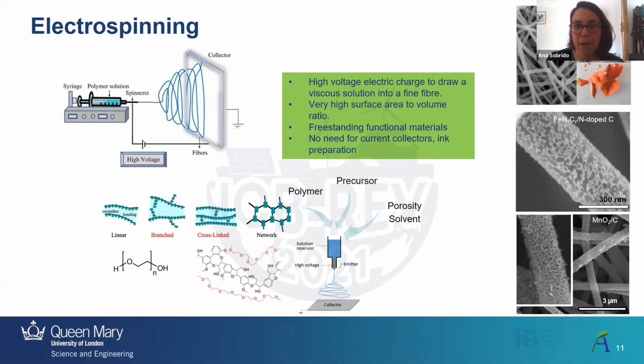And that way we have prepared different fibers. This is just an example of some of the fibers that we prepare in the group. These ones are tantalum nitride. As I say, it's a ceramic. Not all of them have to be carbon based or polymer based. It was actually tantalum oxide that was then nitrided under ammonia gas.